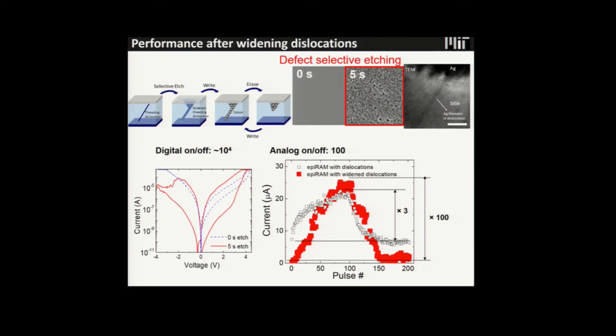The dislocation widening technique was developed 20, 30 years ago in the silicon germanium community. People didn't want to do TEM to count the dislocations, so they made a chemical solution to open the dislocation pipe so they could measure the number of dislocations. That is a characterization technique. Here we use that technique to widen the dislocation space so it can accept more silver ions, so then we can have a higher on-off ratio. By this idea, it completely works. As you can see, the on-off ratio is tremendously improved. Its digital on-off ratio is 10 to the 4th by opening up the dislocation.